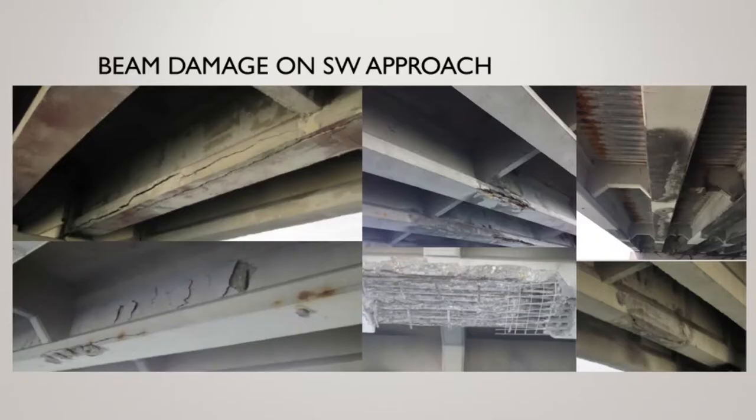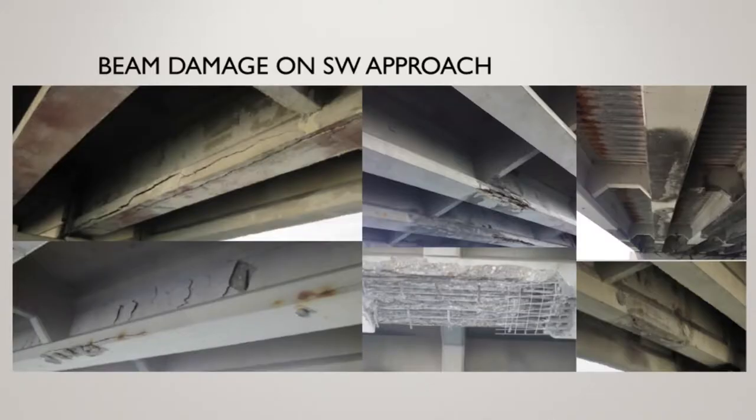We see that here — here are some pictures of the worst stuff, and this is what happens. Just as a side note, these are what we would call old concrete. In 2003, we went to high performance concrete for all new bridge elements and rehabilitated elements — low permeability, pozzolans and that sort of thing. But these are old, porous, spongy concretes. And so you see the effect of the salt getting in: delaminations, spalls, and constant repairs.